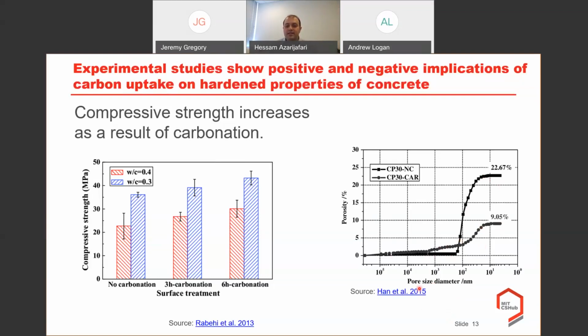And you can see the pore size diameter. So here, the smaller pore size diameter and distribution means that we have a denser matrix and denser binder in hardened concrete. And we are more interested in this region from 10 nanometers to 1,000 nanometers, where those pore sizes play major roles in permeability and mechanical properties of the mixture. This significant drop in the pore sizes and the pore quantity of the mixture, the porosity of the mixture, shows how dense the mixture is and the impact of carbonation in making the mixture denser.